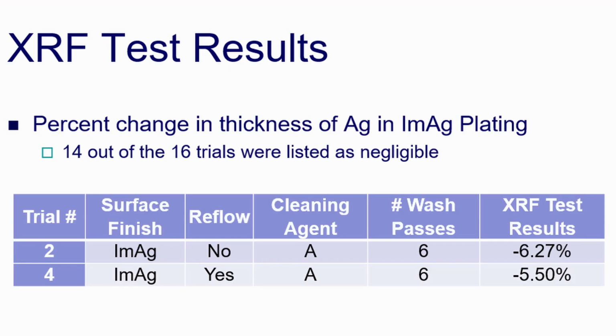In the case of immersion silver, however, three cleaning agents were found to be fully compatible with no significant changes in the thickness, whereas one cleaning agent, the alkaline uninhibited surfactant-based product, showed more than a 5% reduction in the thickness of the plating. This showed that plating is getting removed, and it further corroborated the results we got using visual inspection as well as the surface analysis tests.